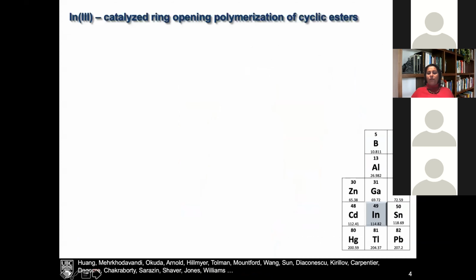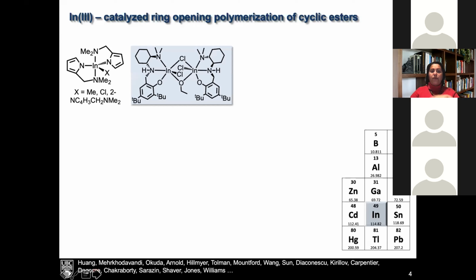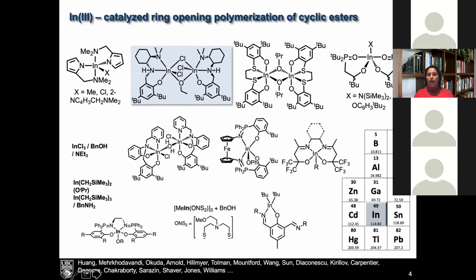Okay, so when we first started this journey into indium chemistry, there was exactly one compound by Wang and co-workers for the ring opening polymerization of cyclic esters. Organic chemists had been using indium-3 for a very long time in a lot of different applications as a catalyst, as a Lewis acid, etc. But in terms of well-defined indium compounds that were used in catalysis, and specifically in polymerization catalysis, there was exactly one. We reported our first example of the system in 2008, and since then, there have been a lot of different systems. They don't fit on a page anymore, and I've stopped adding to the slide. The slide stopped getting updated a few years ago.